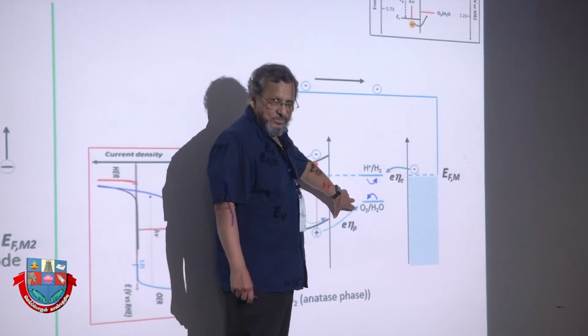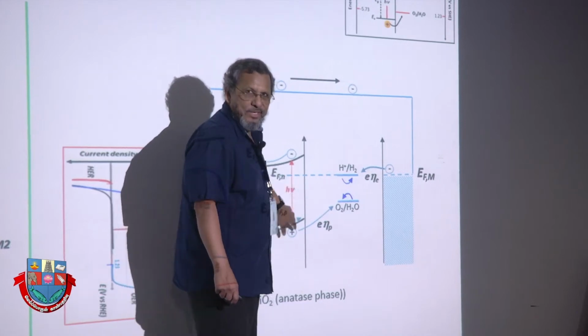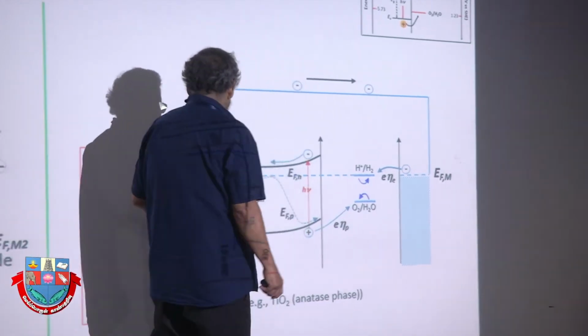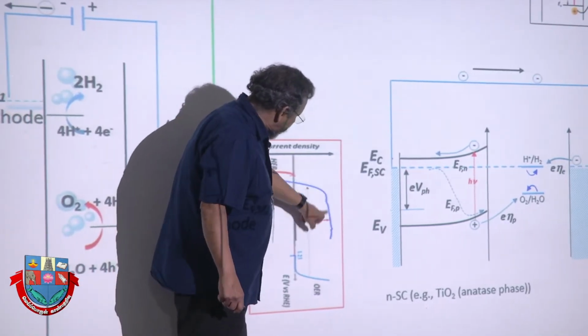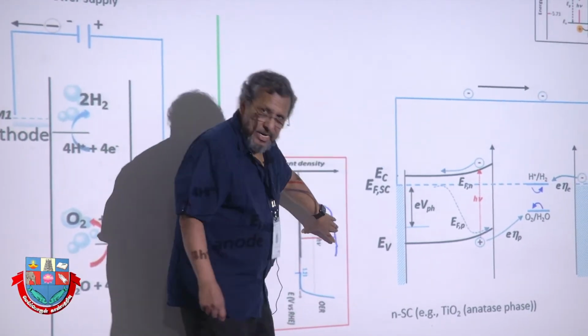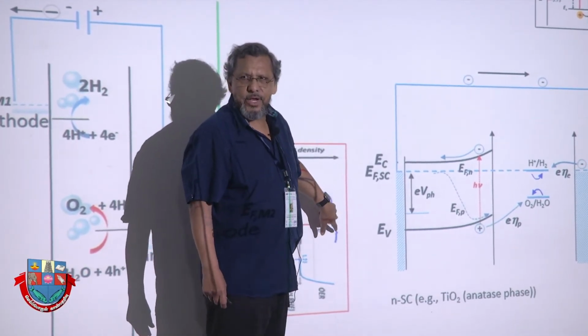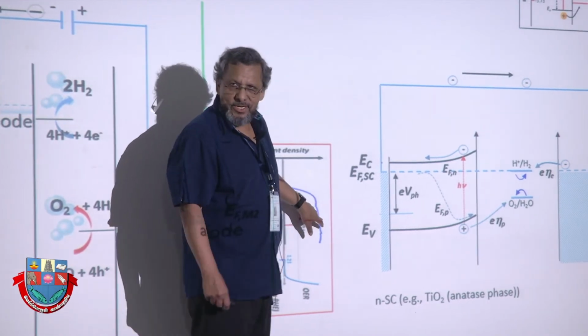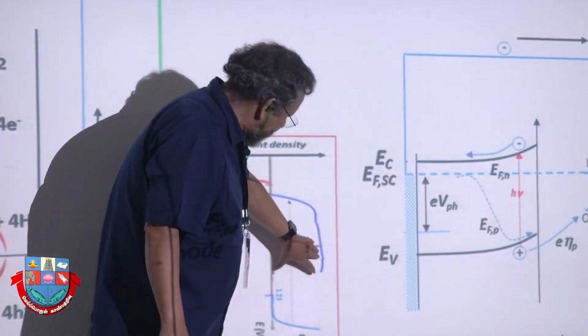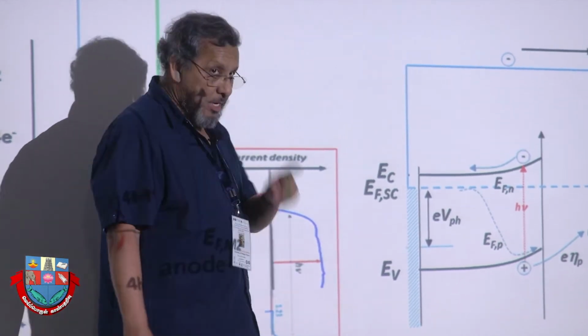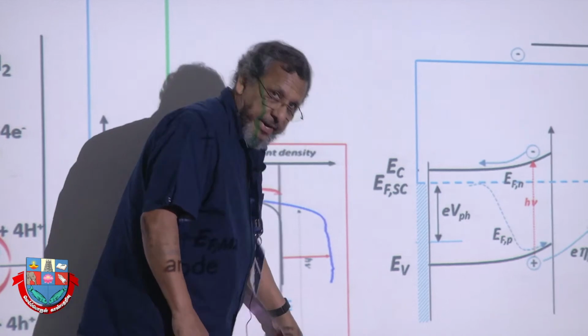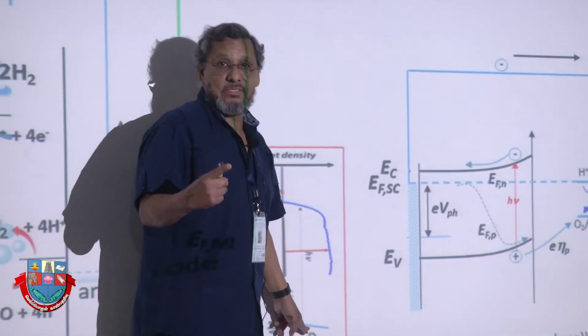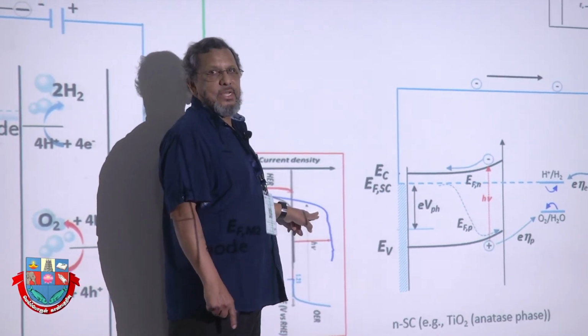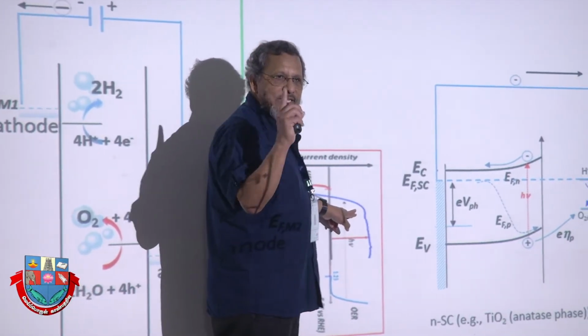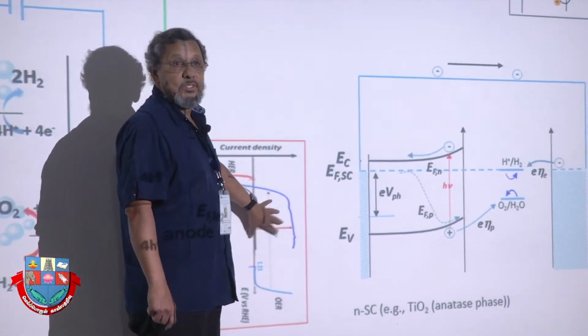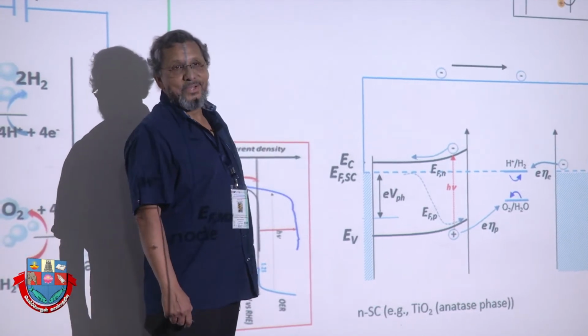The charge transfer here is so complex that I don't know how many hours it would take to explain what happens at the interface. But believe me, this photocurrent, put on the same scale, corresponds to the oxygen evolution reaction. We coupled that with differential mass spectrometry, and indeed, this belongs to the oxygen evolution reaction. Now, what I want you to compare, young guys, is that this process carried out on the metallic electrode catalyst is shifted here. And that is the stored energy released by the impact of photons into the semiconductor electrode. And that is the beauty of photoelectrochemistry.